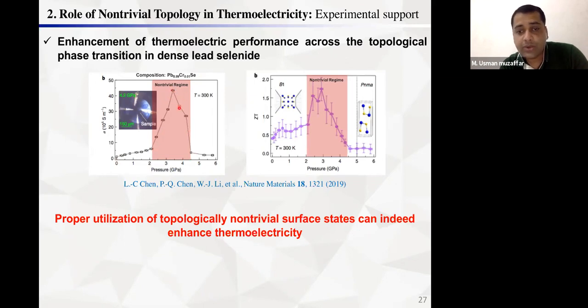So they found that in this temperature and pressure regime, the system is in the non-trivial regime. Then they calculated the ZT value in this regime, and found that the maximum ZT is around 1.7, which is much larger than at atmospheric pressure. So from here we can conclude that the proper utilization of the topologically non-trivial surface state can indeed enhance the thermoelectricity. The topological surface states are good, but they should be close to the Fermi level, so that they can take part in the transport properties.